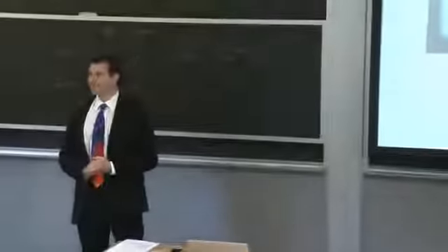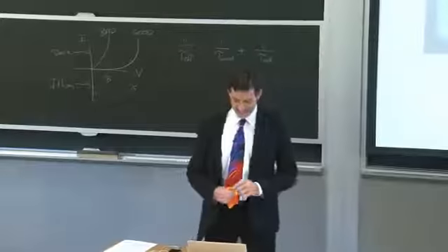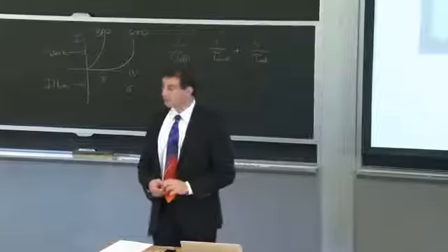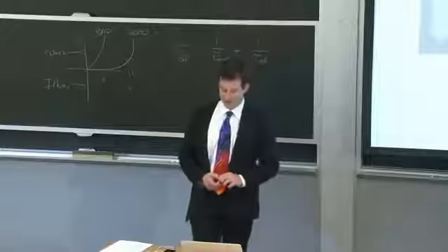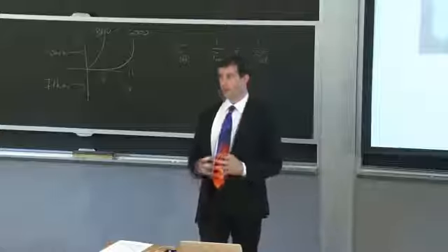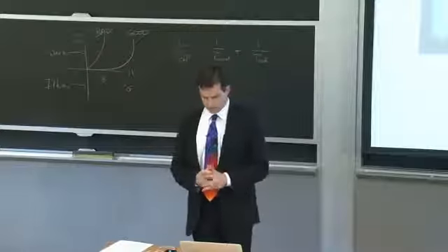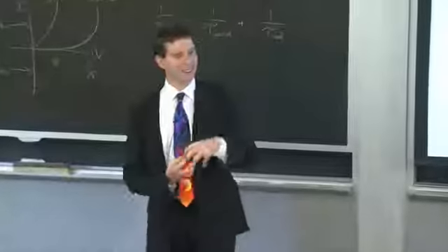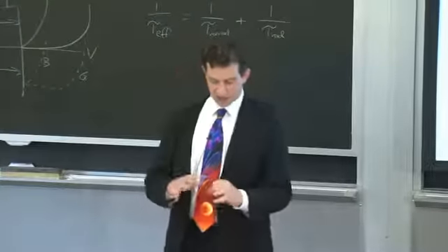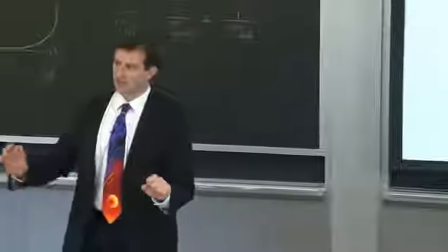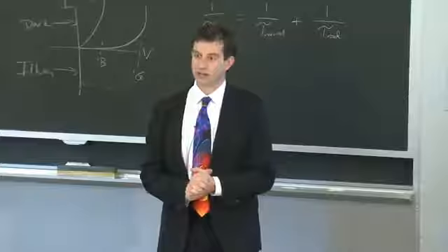Any questions about that? Yeah? What fraction of radiative recombination is then reabsorbed by the material? Is it possible to figure that out to a high degree so you get a quantitative sense of how much it's radiating? Sure. So the question pertains to photon recycling and how many photons that are radiatively emitted get reabsorbed by the material. That would depend on the optical path length inside of the material. You can assume that carrier emission is fairly isotropic in nature, that there's not any preferred direction, unless you have a dye molecule that's designed in a certain way to emit light in a certain orientation. So you can assume that the emission in most materials is isotropic, and then it's just a question of ray tracing to figure out what the optical path length is. Compare that to the optical absorption coefficient in the material, and you get your answer. What fraction of light gets reabsorbed?